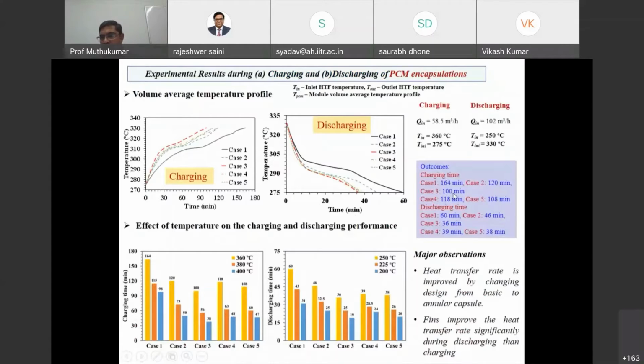So there is a comparison of case 3 and case 5. You can see here, their charging times are more or less the same. But in case 5, you will have 50% less material requirement. In the discharging process too, case 3 and case 5 are more or less the same. So by having this kind of configuration, you can reduce the material requirement by 50% without compromising the charging and discharging rate. Like this you can do it.